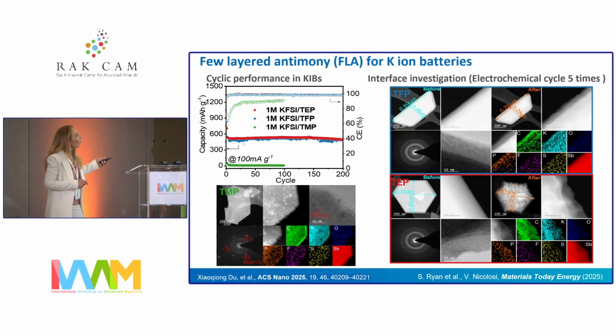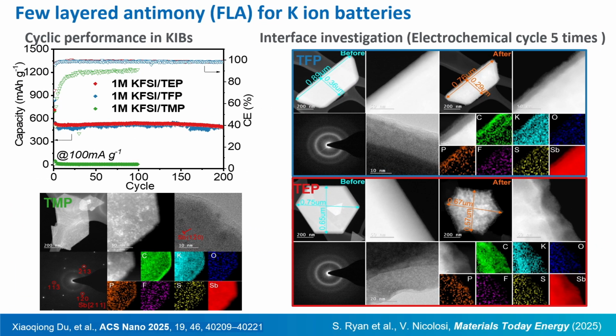Don't focus on that. The take-home message here is that, indeed, the trimethyl phosphate actually didn't work at all for us, at least in the first instance, while the TFP and the TEP worked much, much better. And this is the reason why, if you look at the pre and the post-mortem characterization of the electrode material, you see that in the triflurophosphate here, the structure is pretty much retained, with a very nice solid electrolyte interface being formed.